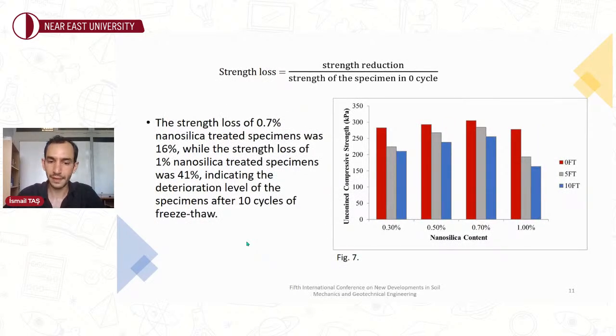The effect of 5 and 10 freeze-thaw cycles was investigated on the nanosilica treated specimens. The strength loss of the specimens is calculated with the formula shown on the slide. Strength loss of 0.7% nanosilica treated specimens was 16%, while the strength loss of 1% nanosilica treated specimens was 41%. Although trace amounts of nanosilica were used in the study, 0.5 and 0.7% nanosilica treated specimens kept the majority of their strength against the freeze-thaw cycles.